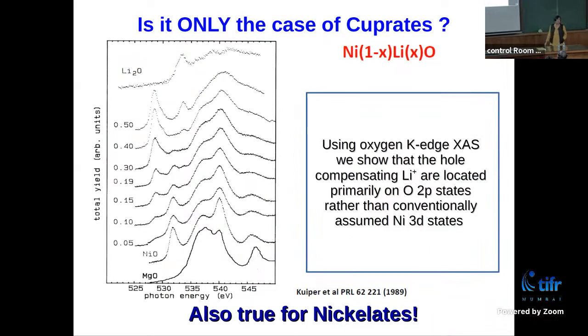And is it the case only for the cuprates? Now there is growing evidence it is not just cuprates. It's even in the nickelates. For example, in nickel oxide, you replace some of the nickel by lithium. That means nickel 2+, divalent, you replace with lithium, which is monovalent. So you are therefore putting in some holes, but the holes, instead of going to nickel, are actually going to the oxygen 2p, which is again proved by the same oxygen K-edge spectroscopy.